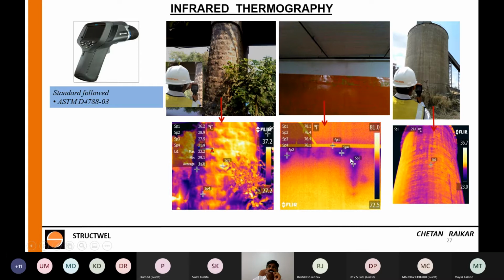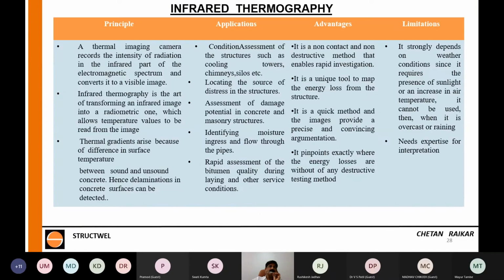In this case, the blue ones are the leakage spots, and as it turns yellow, it is drier. So these are the locations, and only at these locations in an RCC wall you can do grouting, and the leakage can stop. These are load-bearing brick stone masonry piers. You want to know whether the piers are hollow, which areas are hollow. This is near surface inspection, not deep inspection. For deep inspection, you have to use radar or ultrasonic. But for near surface inspection, infrared is a very, very good tool.